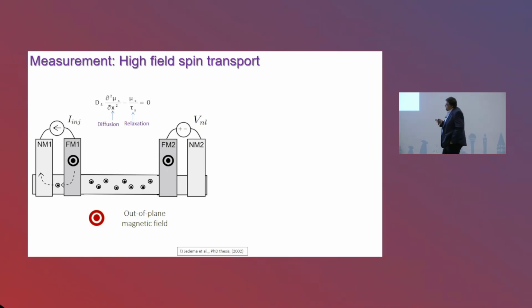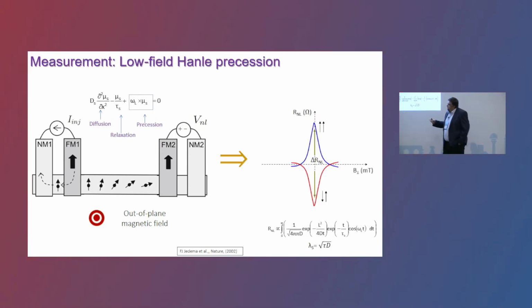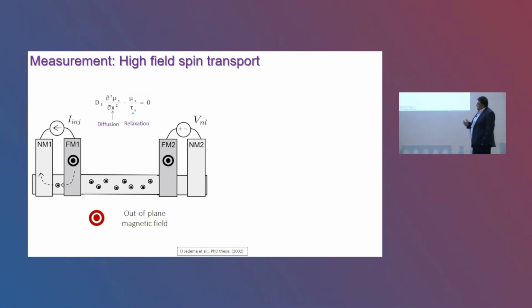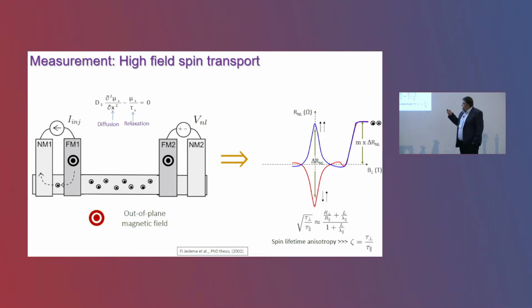The third measurement one can do is the following. In the Hanle curves, I mentioned that you are just applying a small magnetic field, and that's sufficient to do the precession. But what would happen if you apply much higher fields? In that case, your ferromagnets, which are polarized along the in-plane, you are forcing them to be out of plane. So both ferromagnets are now out of plane, and the spins that you are introducing into the channel are also pointing out of plane. This is a bit different from the other measurements, because in the previous ones the spins were just lying within the plane. Now you are forcing them to be out of plane, and this is the typical signal that you would get.